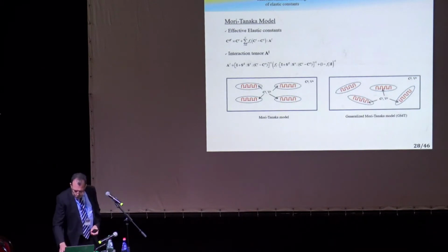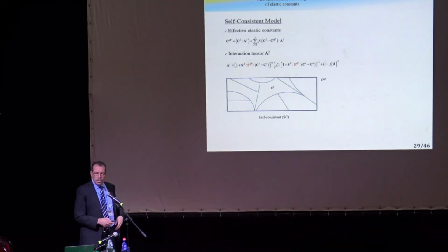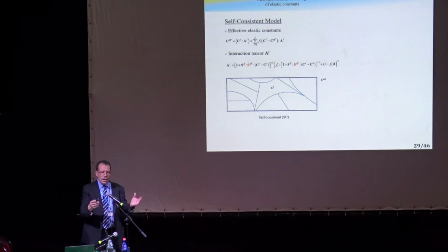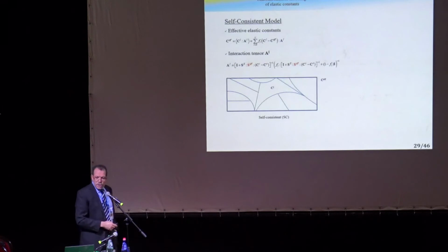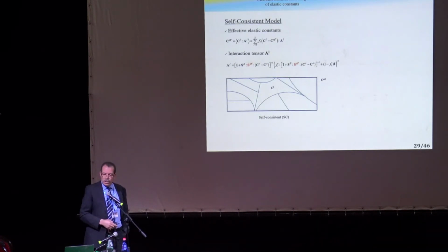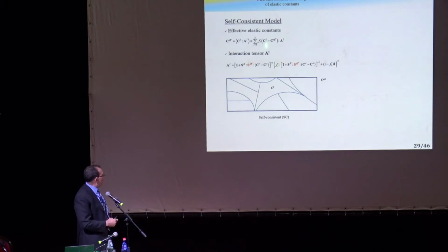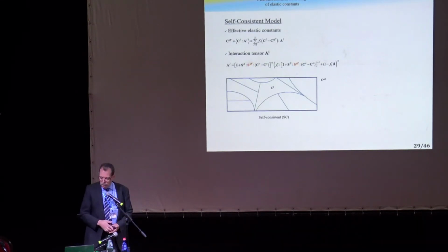We can also use a self-consistent model. If you use a self-consistent, we use a double inclusion model, and we make sure that the volume fractions in the double inclusion match somehow a polycrystal, but a polycrystal made of two-phase inclusions. In this case, the reference medium is no longer the matrix like in Mori-Tanaka, but the effective medium. So this is the effective elastic stiffness, given by this relationship here, but now the interaction tensor depends on the Hill tensor and on the effective stiffness or compliance tensor.